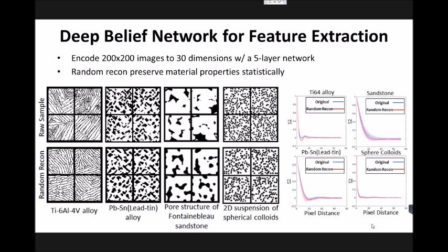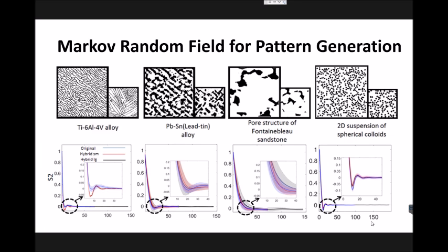However, by the nature of the deep belief network, the reconstruction size could not be larger than the input samples. In this case, a hybrid model has been built by using a Markov random field to model the distribution of the activation of local material microstructure patterns. As we could see, the reconstruction size is no longer an issue, and the statistical similarity is still preserved.